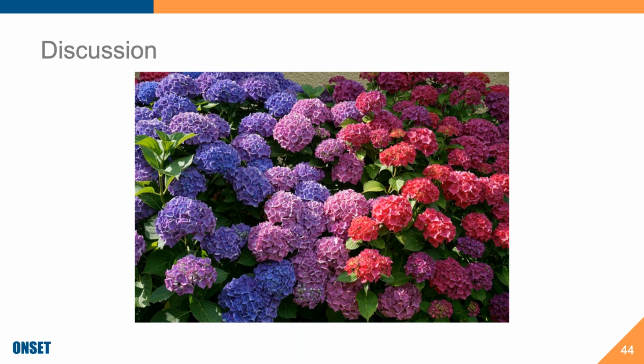A question for storage. You said to store it in solution. My probe has a cup with a sponge. Is keeping it stored in KCl solution the best? So your probe has a cup with a sponge. Yeah, so this is actually an interesting thing that I'm seeing between manufacturers as well, and that is whether you're storing it in a solution or whether you're storing it in a moist environment. And if that's the case, then for instance, your cup with a sponge would be probably the moist environment that I'm reading about. And it's really up to the manufacturer.